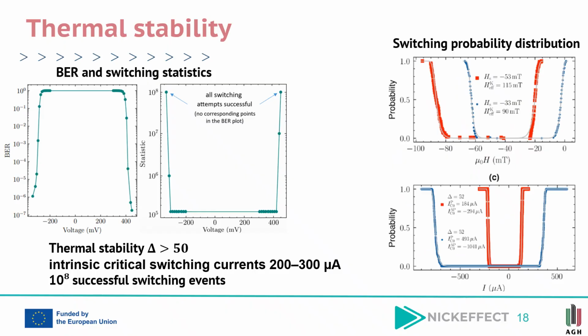In addition to static and dynamic switching measurements, the thermal stability and reliability of the optimized MTJ nanopillars were investigated. Thermal stability is one of the key requirements for reliable STT MRAM operation, since it determines long-term data retention and switching robustness. The analysis was based on statistical fitting of the switching probability distributions for both switching directions. The experimental data were fitted using a thermally activated switching model. The switching probability distributions presented on the right were measured as a function of magnetic field and switching current.